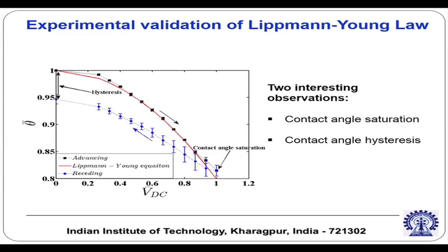So, you can see that there are two interesting observations. This red colored line with black squares on the top of the red colored line is a representative of the advancing contact angle. That means what you do is that you go on applying the voltage and the contact angle decreases. But you can see that beyond the critical voltage, the contact angle does not go on eternally decreasing. It comes to a saturation. This is what is observed in experiments.